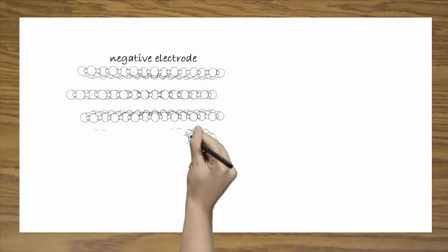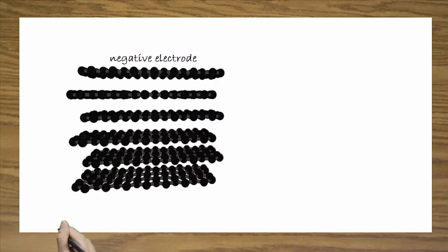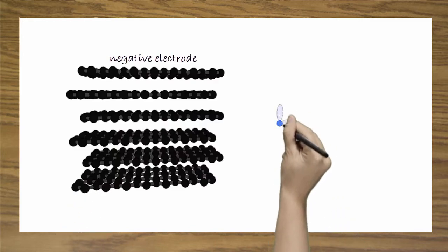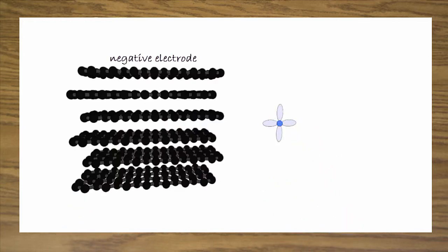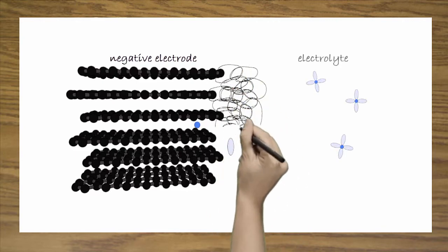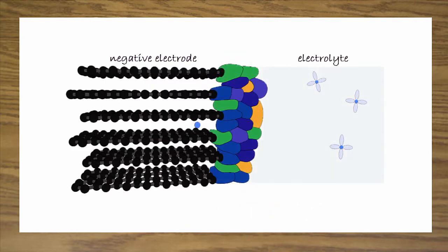Let's now take a closer look at the negative electrode. On the negative side, during charge, the lithium ions, solvated by solvent molecules, approach the surface of the graphite. After losing the solvation shell, the lithium ions are inserted into the graphite sheets. At that step, the potential of the negative electrode is very low, and there is a thermodynamic driving force for electrolyte reduction, leading to the formation of decomposition products that deposit on the surface.